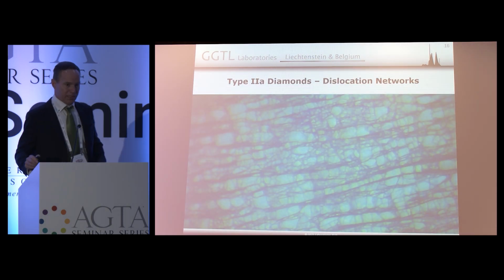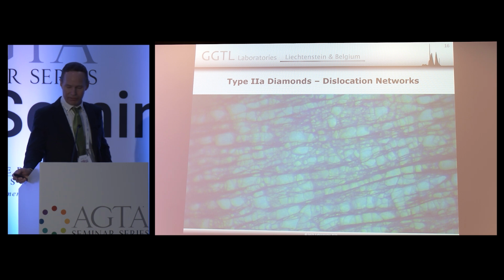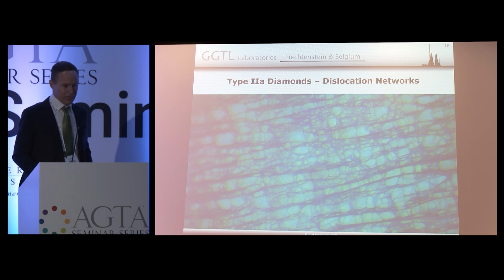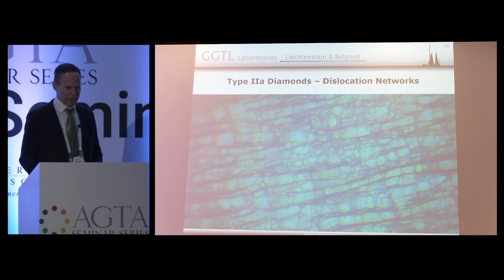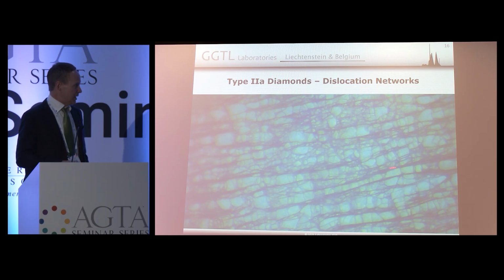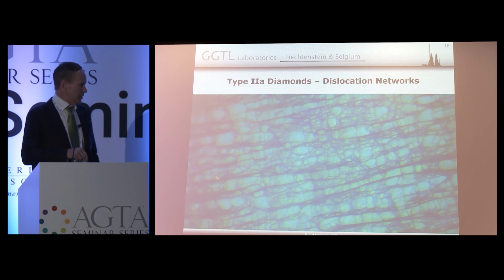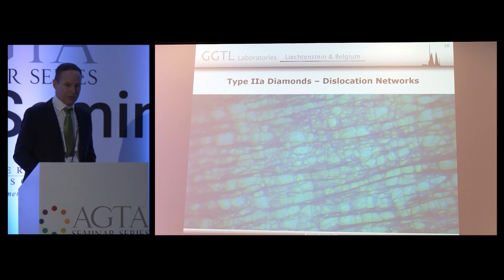And let's look at type 2A diamond. Type 2A diamond is very different from type 1A material. In type 2A diamonds, we see commonly these so-called dislocation networks. So this is relatively high magnification. This is probably about 2 millimeters in a natural diamond. You see these spider web-like features in a colored fluorescing matrix. This is very typical for natural type 2A.